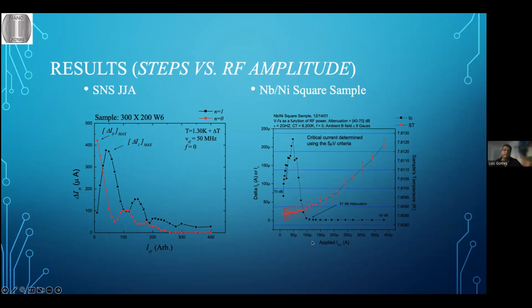But as we increase or reduce the attenuation, we are heating the sample. For small values of the applied current, there is almost no change in sample temperature. But as we increase that value, the temperature heats up. So in the measurements over here basically nothing is happening, but we cannot be certain that we are at the same state of the system because the temperature changes. But how much does it change?